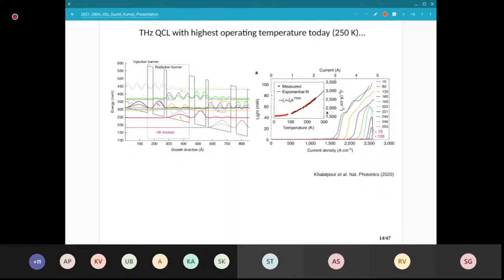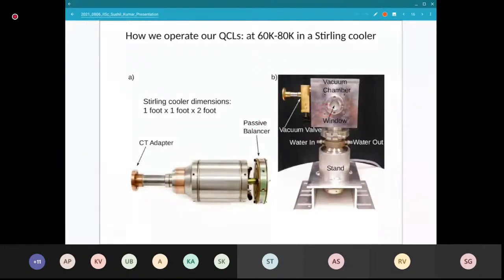Any application that will use these lasers will have to consider that they will be working below 100 Kelvin. So you'll have to cool them with liquid nitrogen, around 78, 80 Kelvin or so. The way we do it in our lab, we use this Stirling cooler.